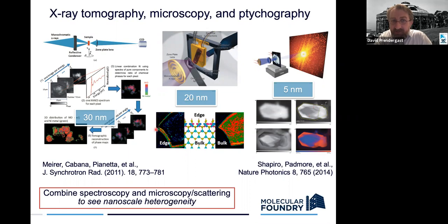And this is looking at the edge of a molybdenum disulfide nanoflake. And you can even begin to see what look like different layers here. And these edge features had some different spectroscopy than the overall bulk of the nanoflake. And we were able to explain that in this case as defects in the edges of the material by just creating those defects in calculations and simulating their spectra.